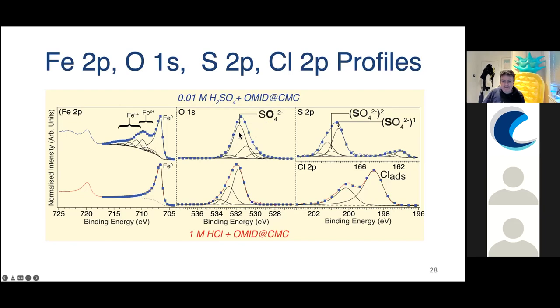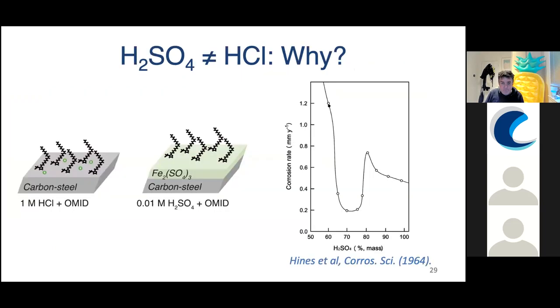If we look at the oxygen 1s signal, we have this intense peak here, which we can assign through comparison with the literature to the oxygen in sulfate, SO4 2-. Then if we look at the sulfur signal, we see actually 2 peaks, and they're doublets, but don't worry about that, 2 features that are due to sulfate in slightly different chemical states. So what we believe on interpreting these data is that we're forming a thin layer of ferric, so Fe3+, sulfate at the surface. That's shown in this cartoon here. So the molecules are adsorbed in some sort of state, but we're not sure what, on not a film-free surface here, but a thin layer of ferric sulfate that's sitting on top of the metallic iron or carbon steel. So why is that?